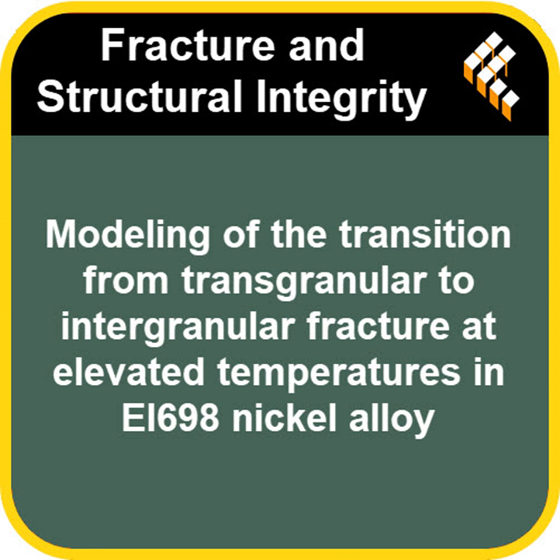Exactly. And one last correlating detail. The model also predicts the initiation of small, separate damage sites, or microcracks, popping up in the grain boundary regions, not directly connected to the main crack tip yet. This aligns really well with actual fractographic studies of these materials, where you often see a sort of cloud of microdamage ahead of the main crack, particularly along grain boundaries at high temperatures. So the model even captures that pre-damaged state. It seems to, yes.